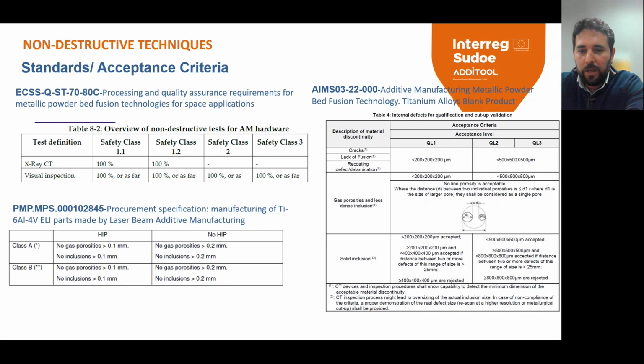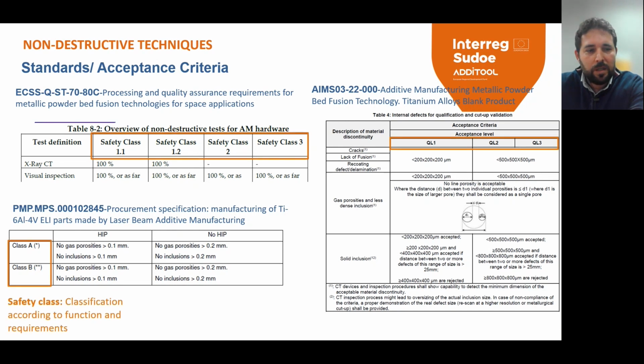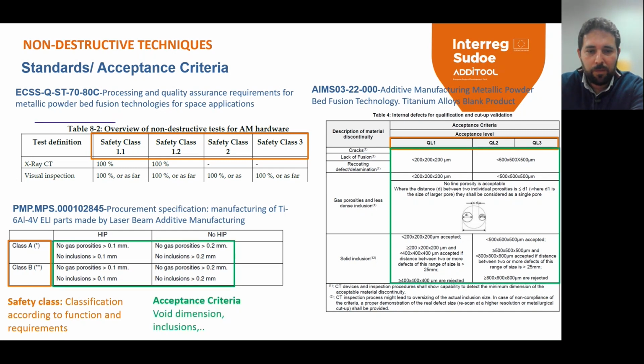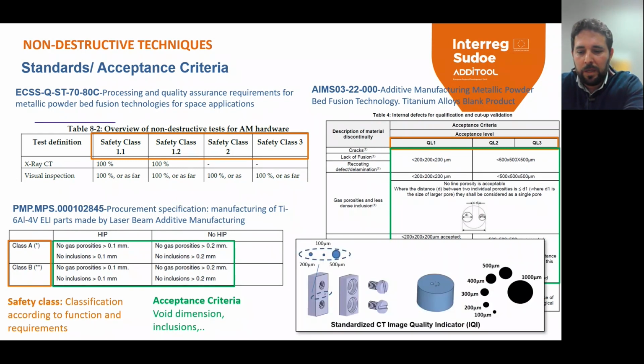The customer has to define the safety classification of the part according to functionality and other requirements. And then the acceptance criteria in terms of gas porosity, inclusions, lack of fusion, etc., is met. And when inspecting flight components by CT, you need to use some image quality indicators together with the component, that is this kind of small parts. It has standardized defects on it, and it is used to assure detectability.